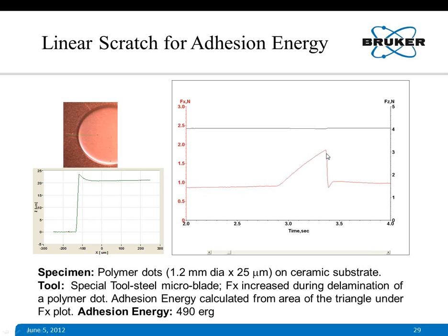It increases linearly and goes down as it removes the dot completely, scratching through the dots. The area under this Fx with distance curve, here it is a time plot, but this can be converted into distance because you know the velocity of the stylus movement. And from this area, when it is plotted with Fx versus d, we can have the adhesion energy